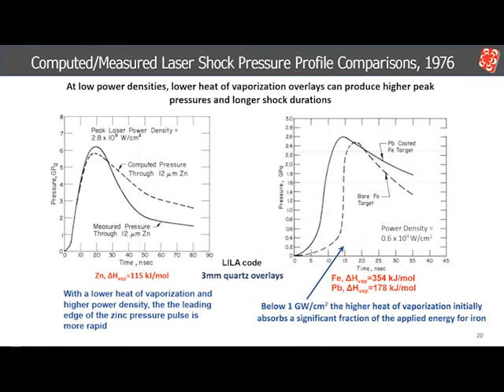To compare the overlays being considered at the time, computations were made to gain a better understanding of how they affected the magnitude and duration of the pressure pulse. The figure on the left compares a computed profile for a zinc overlay with the measured profile. The rise time and peak pressure are in good agreement. However, the back of the measured pressure pulse decreases more rapidly than the computed one.